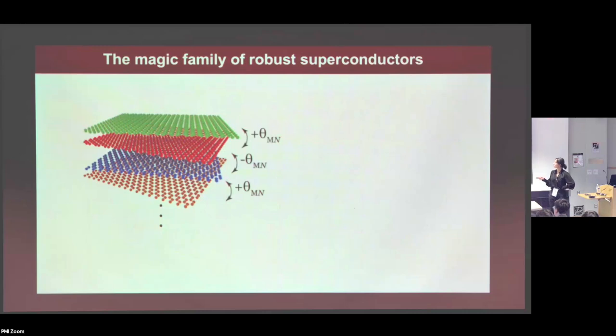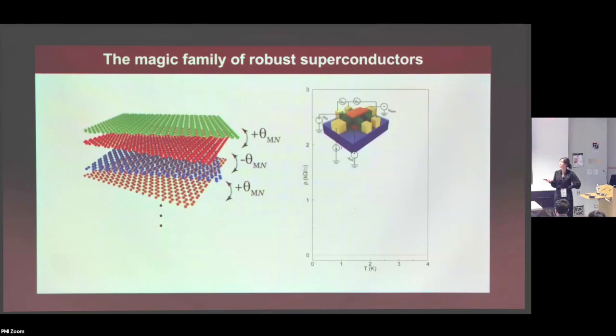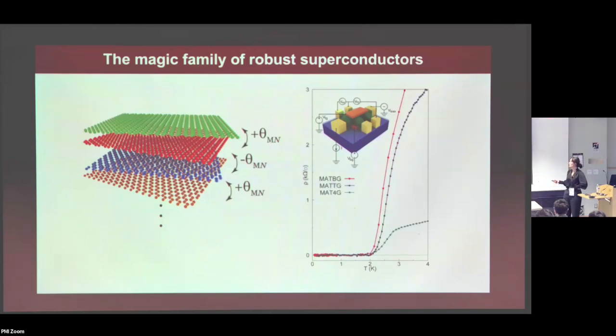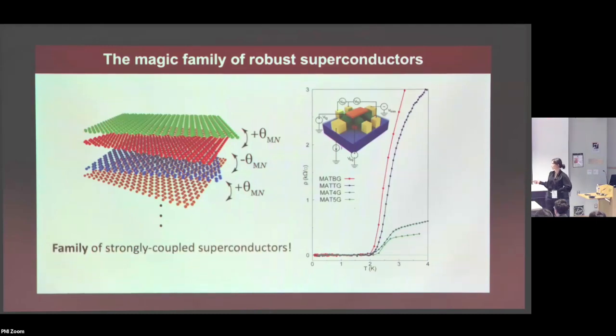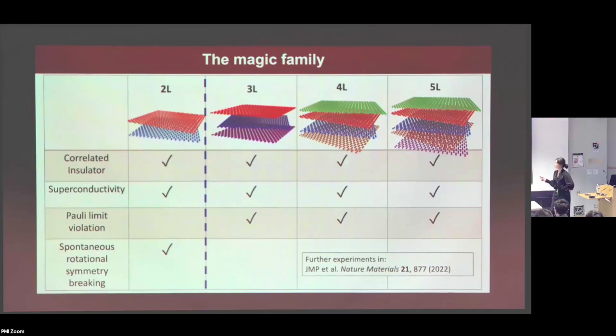Okay, so we have experimentally realized this system up to 5 layers. You can see the resistivity versus temperature for magic angle twisted bilayer graphene, twisted trilayer, twisted 4-layer, and 5-layer. They're all pretty superconducting. So we have found this family of strongly coupled superconductors now. And an obvious thing that you also want to study is to compare and contrast what these family members have in common and what's different. I'm not going to go into detail. If someone is interested, you can read this paper.